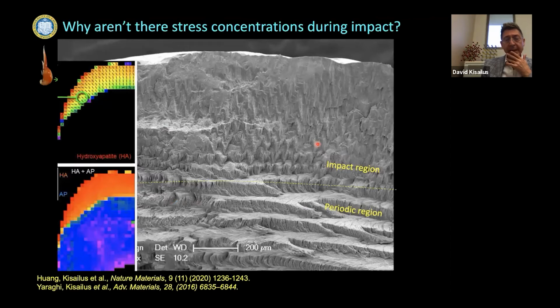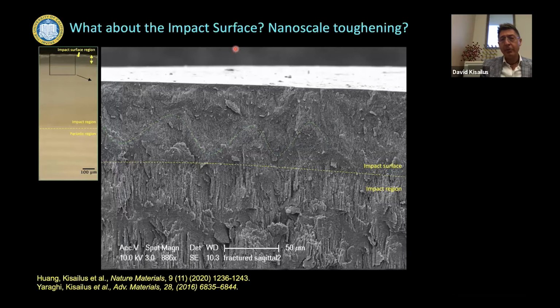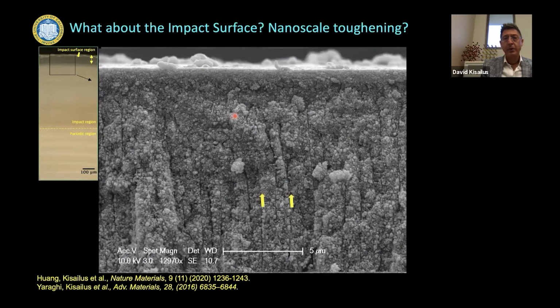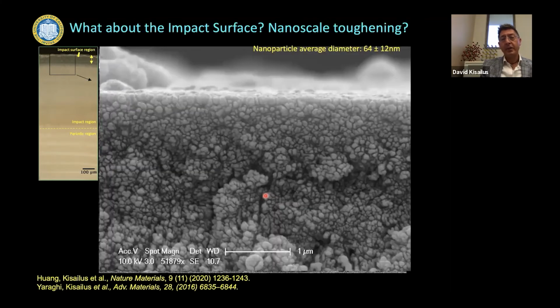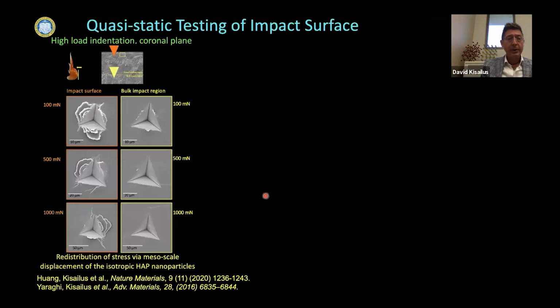Okay, so as I mentioned, I want to focus more on this impact surface. So why don't we see stress concentrations during this impact? Here's your Bouligand structure. Here's your impact region. But at the very top of the club, roughly about 50 microns or so on the surface of the club, there are these nanoparticles. These arrows here show the pore canals that actually transport mineral during the formation of the club, but that's another story for another time. The outer surface of this club is coated with nanoparticles that are roughly about 60 nanometers in diameter, surrounded by some organic matrix. And we initially nano-indented the surface, the impact surface where those particles were located.